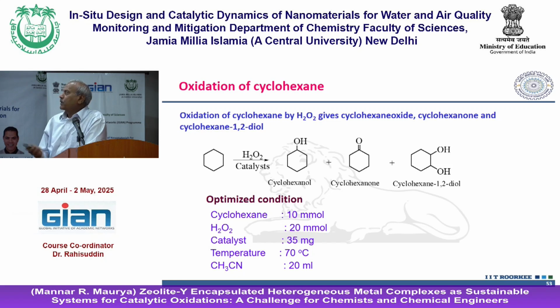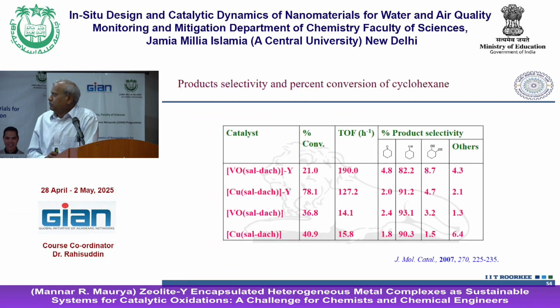I'll show you that. Now we have a cyclohexane. You can do that oxidation easily. Conversion is a bit less, but under optimized condition, you will see that this is going to give you the product. Low conversion is not that good, like we have taken with this vanadium compound or the copper compound. With cyclohexane, oxidation is not an easy job.